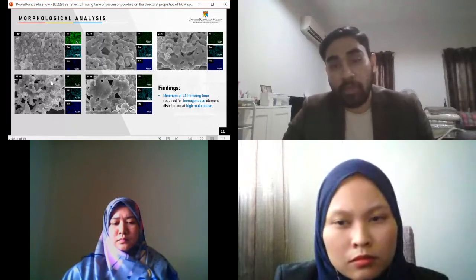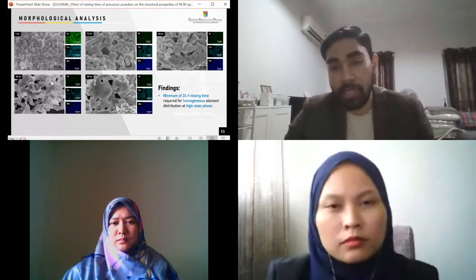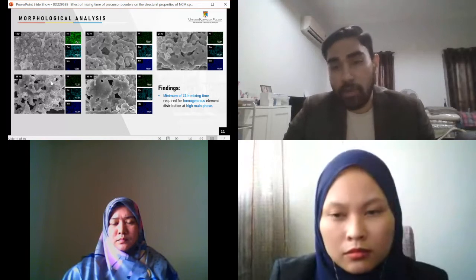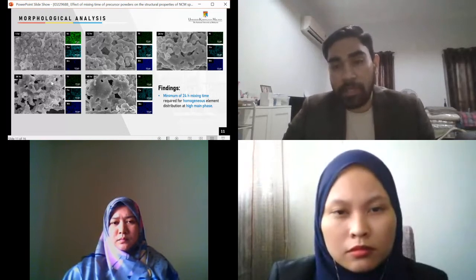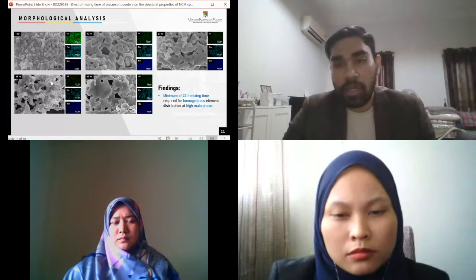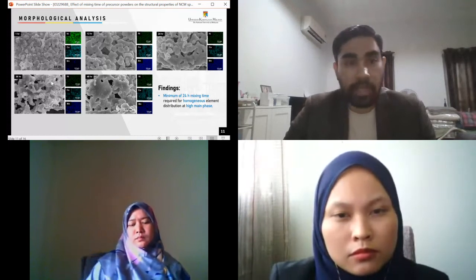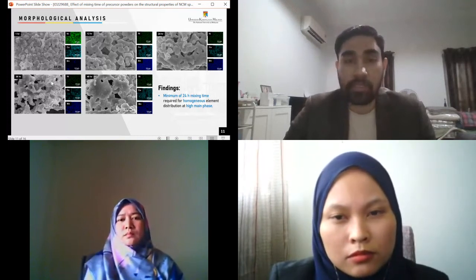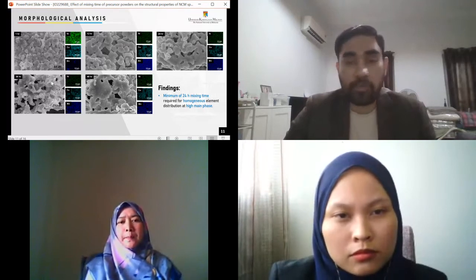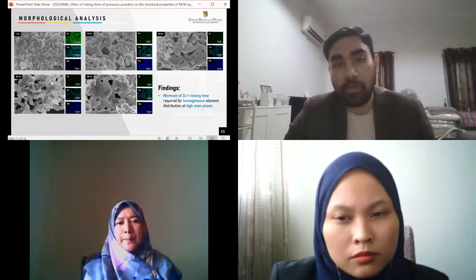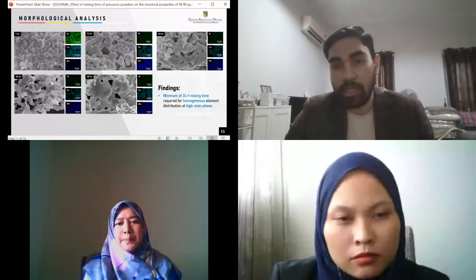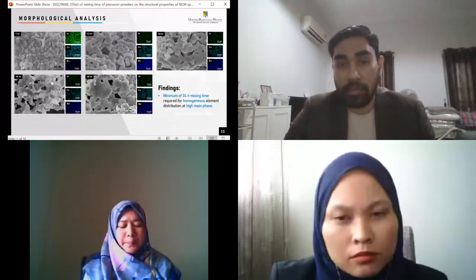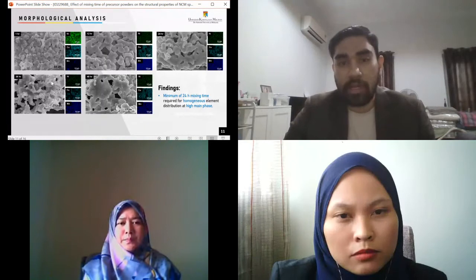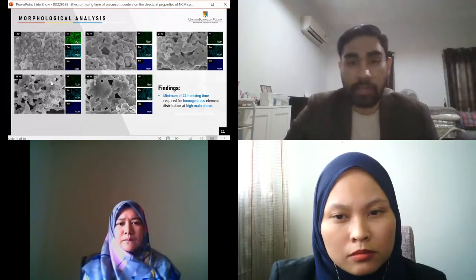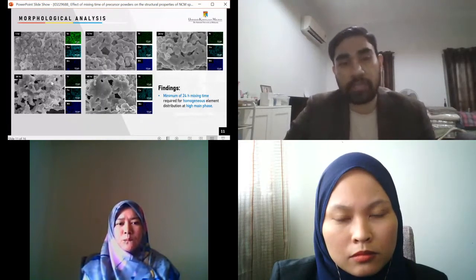And after 24 hours, there is no significant change in the distribution, meaning that at 24 hours, the elements started to distribute at maximum capacity, so that no significant change was observed. So from these two analyses, we can see that a minimum of 24-hour mixing time is required, not only for homogeneous element distribution, but also to have a high main phase presence in the structure of the spinel.